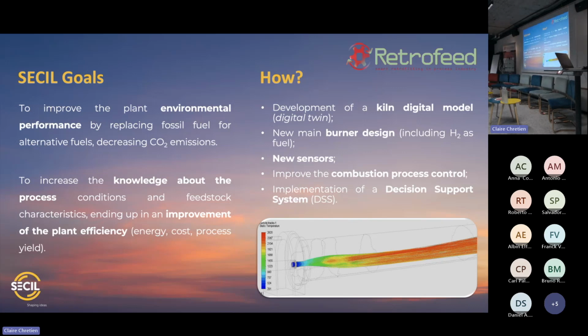And that's why we are looking for a strong new fuel, and that's why we aim to go to green hydrogen. So we need to complement the RDFs, the tires that we are using, and we still have, as I said before, a substitution rate of about 50%, but we need to go higher. Somehow we need to complement this energy, because to achieve a good clinker quality, we need at least 1450 degrees Celsius. Otherwise, we don't achieve a very good clinker quality. So for these high temperatures, we need something else to compensate the low specific heat of the RDF. So that's why hydrogen is so important for us.